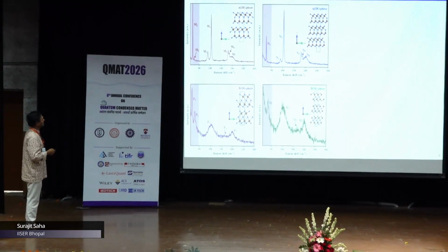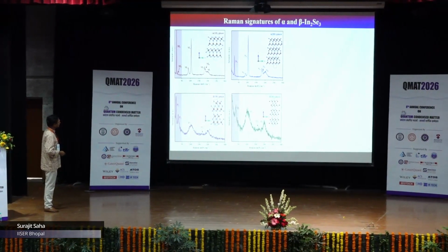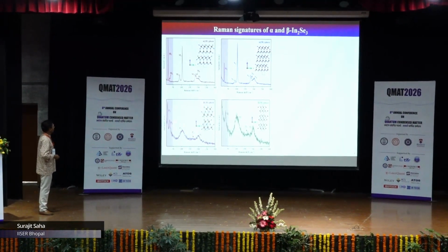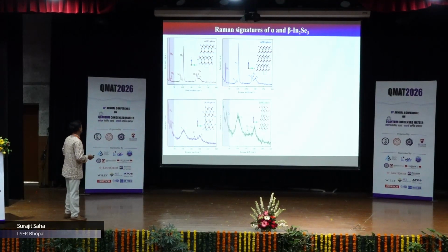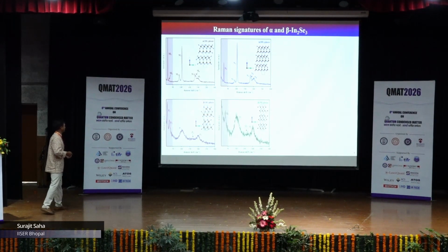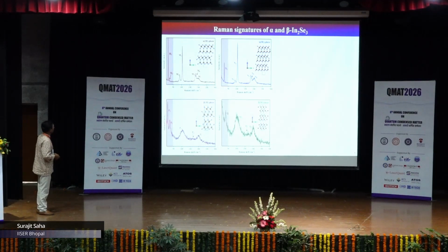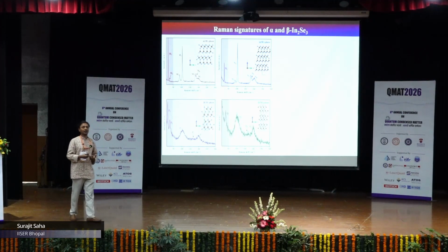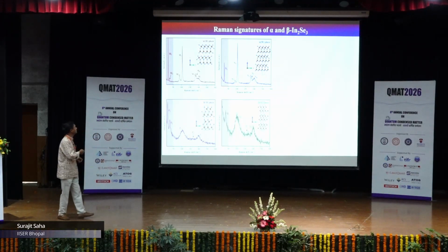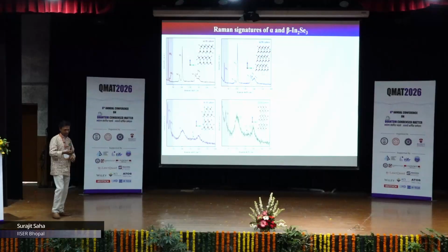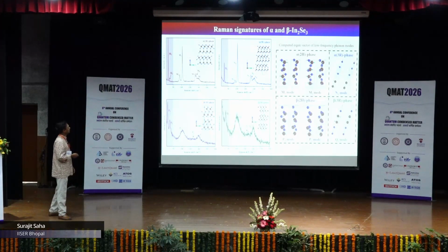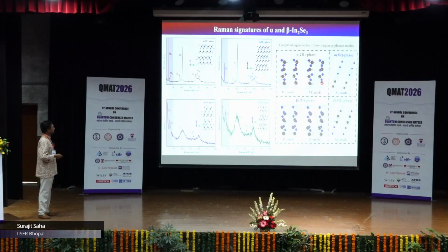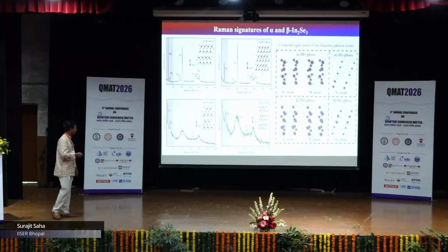And as compared to the alpha stacking, the beta stacking is here. You can see the spectrum itself is quite different, and that's also connected to the metallic nature of the beta phases. So here you can see there are 2 peaks, and these 2 peaks correspond to the 2H structure, and a single peak connects to the 3R structure. So these will be the signatures for us to identify whether we are in alpha 2H, alpha 3R, beta 2H, or beta 3R. And let's proceed now. These are the calculations done by Ravi and Mitanshi. So these are the various vibrational modes that are responsible and would be our signatures to look at